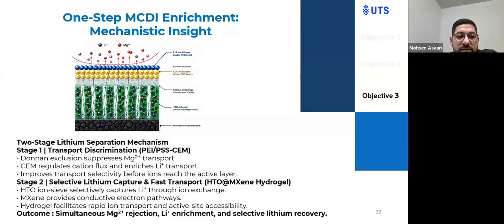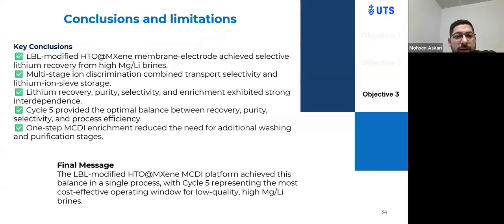In the first stage, based on Donnan exclusion, the cation exchange membrane suppresses magnesium transport, regulates the cation flux, and enriches the lithium transfer. On the other hand, in stage 2, the HTO MXene hydrogel has fast and highly selective lithium adsorption, in which the hydrogel facilitates rapid ion transport and active site accessibility. The outcome is simultaneous magnesium rejection, lithium enrichment, and selective lithium recovery.